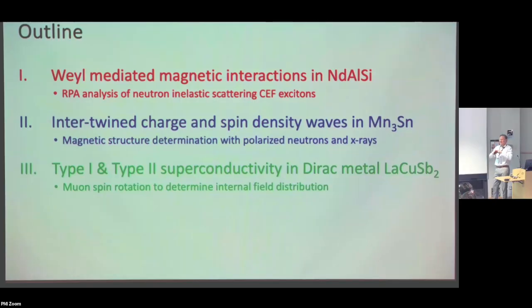And that's because it is actually a Dirac semi-metal, but then undergoes a phase transition to an antiferromagnetic order, which has the symmetry of a ferromagnet. So it has a spin-split electronic band structure and actually has an anomalous Hall effect in the presence of almost no magnetization. There is actually magnetization, but it's extremely small magnetization.